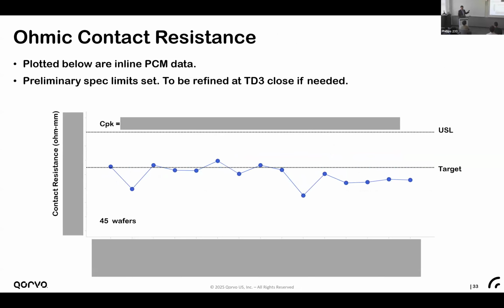And the contact resistance is what we measure from our inline DC measurements. During the wafer process, we have multiple characterization steps in the middle of the process. Once we have all these metal pads fabricated, you go to measure these DC, sometimes we measure CV, right? So all of these things need to be shown in this SPC chart.